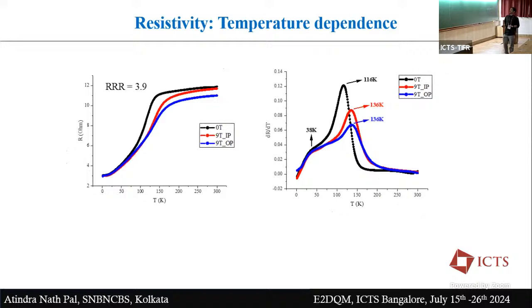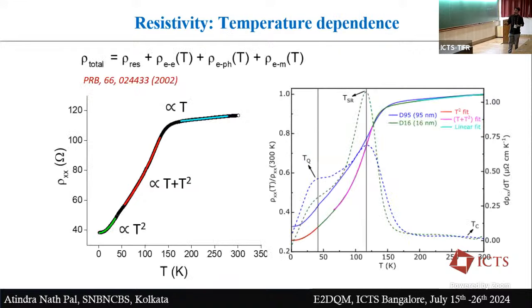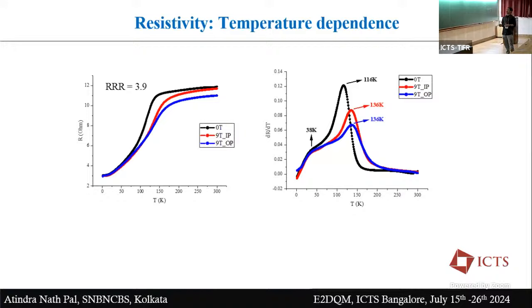Okay. Now, to understand the low temperature part, electron-electron interaction can give you T square, and electron-magnon can also give you T square. So to understand which is dominant in which case, we did the magnetic field dependence. And if you do the magnetic field dependence, what you observe is that at low temperature, till 40 Kelvin, you see almost no magnetic field dependence of this resistivity curve, very weak dependence. But above this hump, you can see that there is a huge magnetic field dependence.